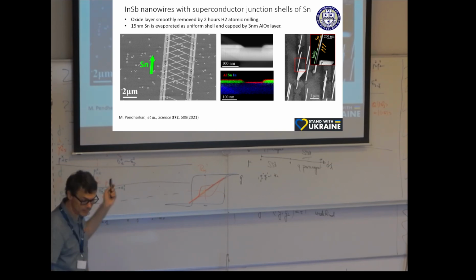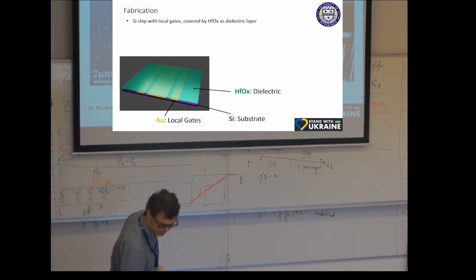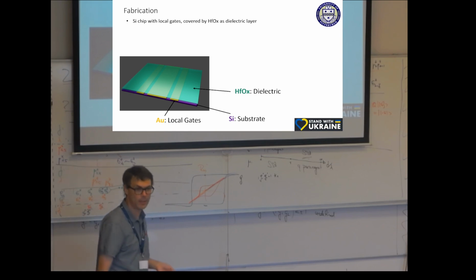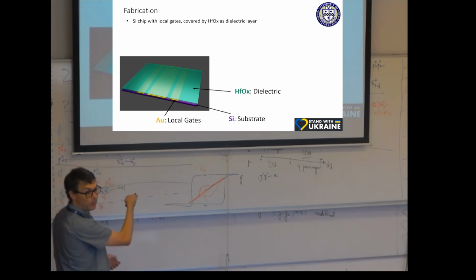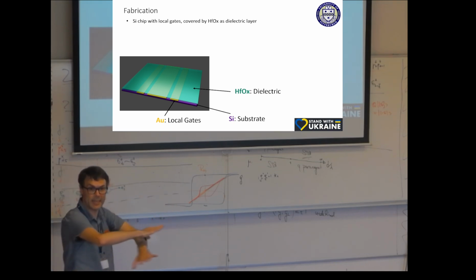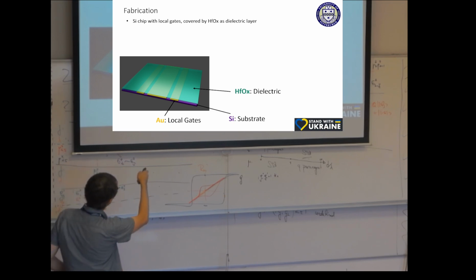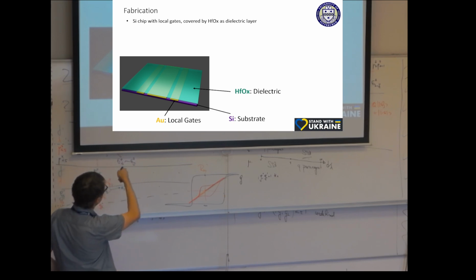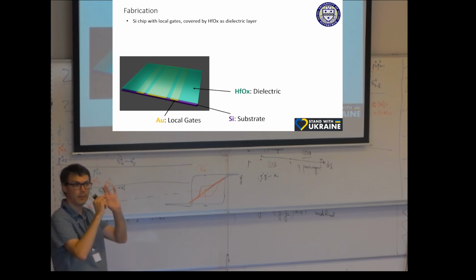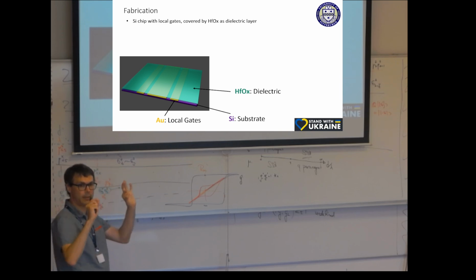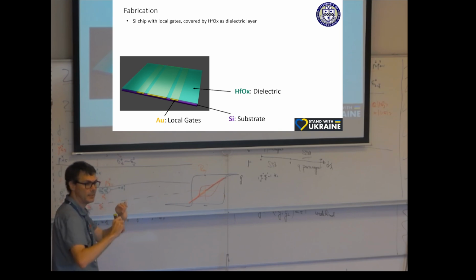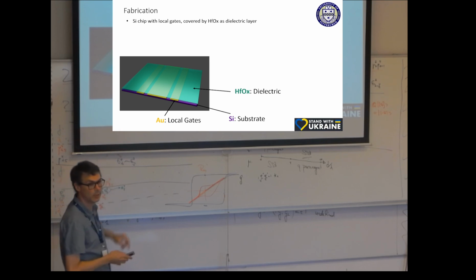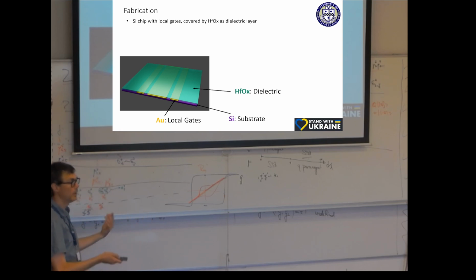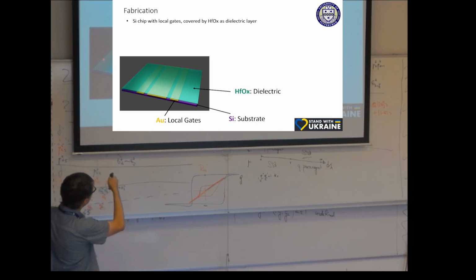Okay, so this is the junction, kind of, and this is how we then make the full device. That's the substrate from before. Remember, there's a substrate like a table. Now, on this substrate, there are these gold electrodes that are very thin. These are 6 nanometers thick gold, and they're electrostatic gates. They can be individually controlled, put voltages on them. And then there's a layer of dielectric, in this case, hafnium oxide.